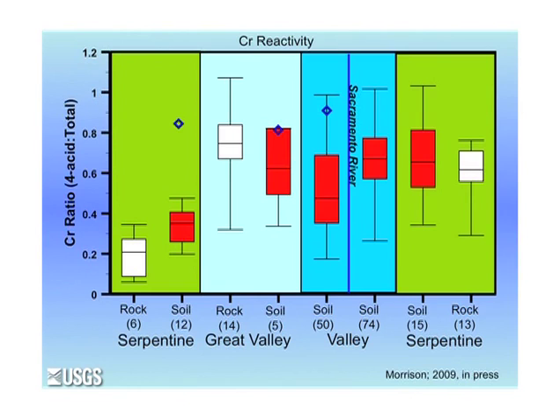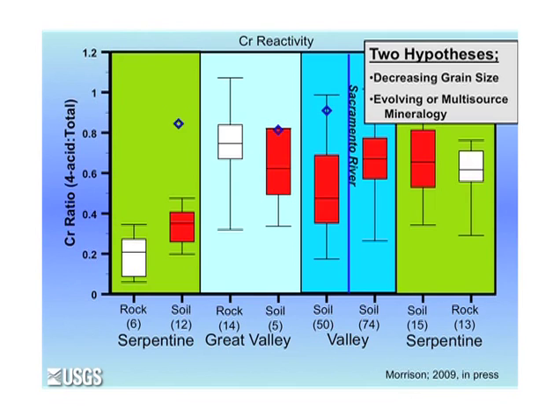So ultramafic rocks, serpentines in the coast ranges are only slightly soluble in the four acids. Here, zero would be insoluble and one would be fully soluble. So only about 20% on average of the chromium dissolves in the four acids. The soil's a little bit more. But as you work your way into the valley, you see a much higher proportion of chromium soluble in the four acids, implying something has changed along the transport path.